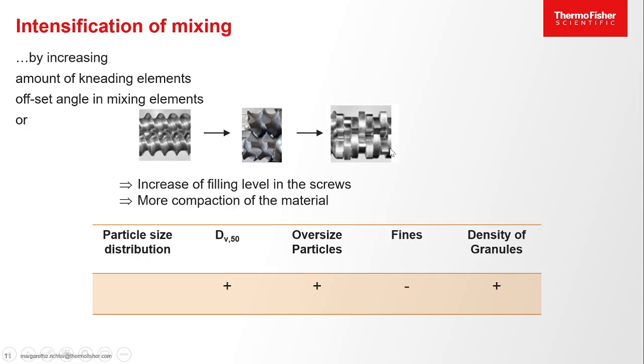And here I can change the angle between these kneading elements and thus densify the material in this kneading section quite a lot. So basically, if I change that by increasing either the amount of kneading elements or the offset angle between these kneading elements, I intensify the mixing that way. And by doing so, I get an increase of filling level in the screws, especially in this kneading section. And this will lead to more compaction of the material.